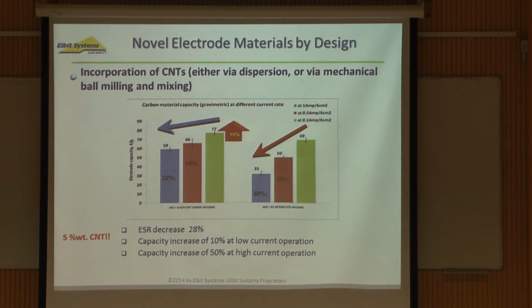And we saw that the inner resistance, due to only 5% CNTs implementation, was decreased by 28%. The capacity increased at low current operation by only 10%, but the good point is that at high current operation, and when you look at those transportation applications, that's what you need, high power and high current operations, the capacity increased by 50%. An increase of a capacity by 50% means that the energy density is increased by 50%.